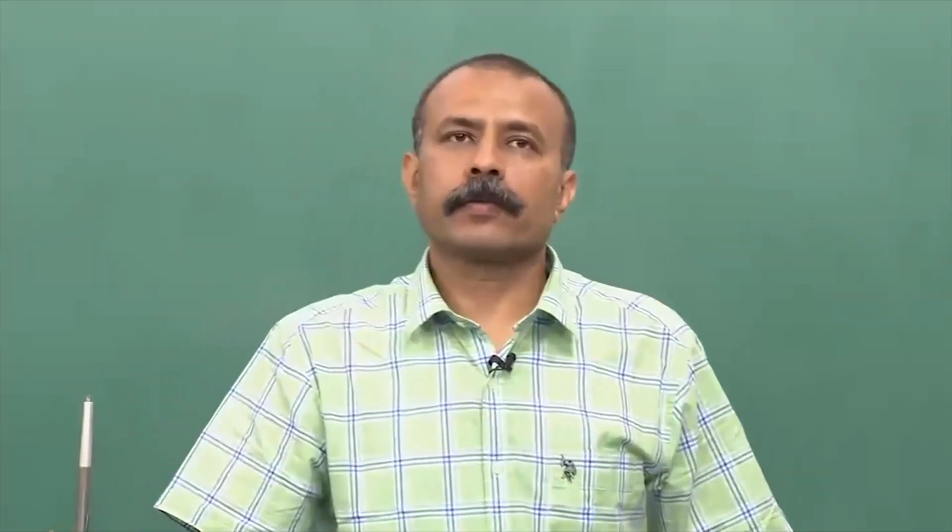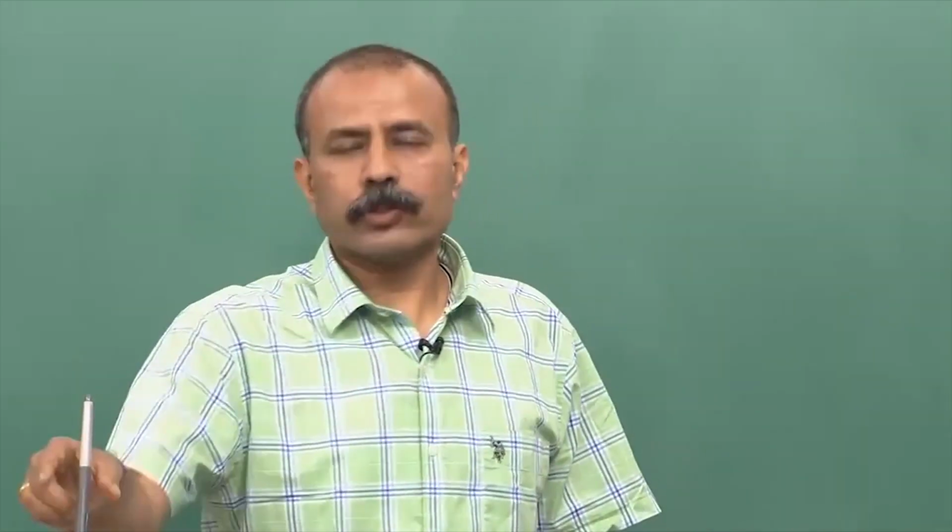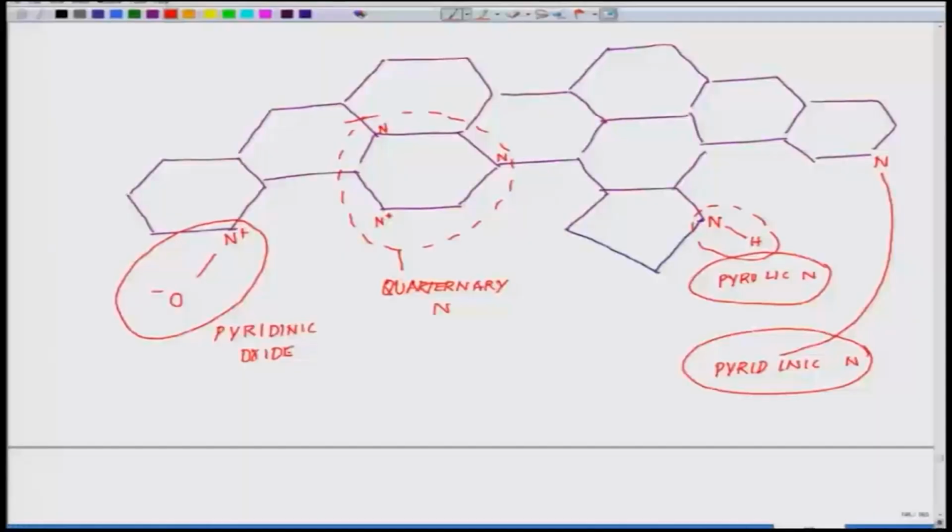So, if you observe in a simple structure of graphene following a very low energy technique, you just expose them to 400 degree centigrade and you get one of the very high quality nitrogen doped graphene. So, what is this? This is essentially nitrogen doped graphene. As a matter of fact, making these kind of nitrogen doped graphene was done in India for the first time.